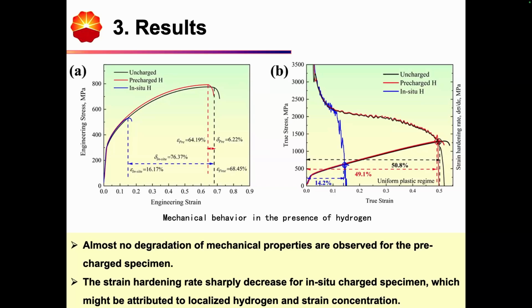For the in situ charged specimens, we can see that the fracture strain sharply decreases, and almost no strain hardening rate plateau is observed for the in situ charged specimens.